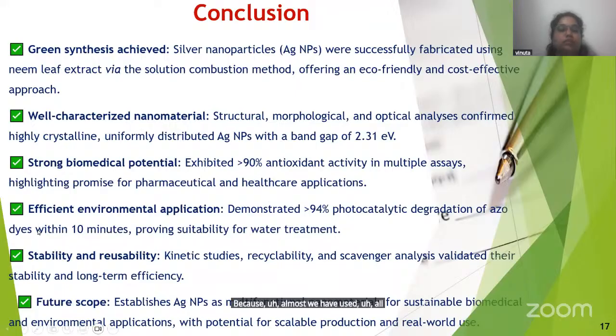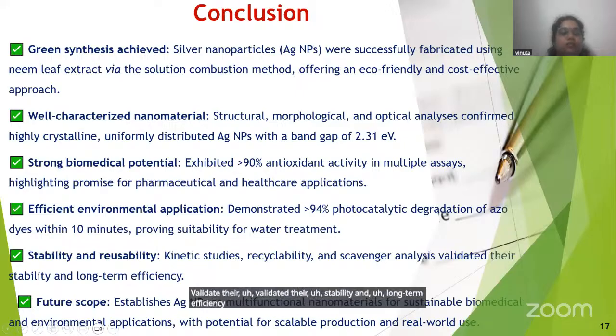So these showed 94% photocatalytic degradation of azo dyes, because we have used almost all the azo dyes, within 10 minutes, providing suitability for water treatment, mainly acidic water. So with the help of kinetic studies, recyclability, and scavenger analysis, their stability, long-term efficiency, and reusability were validated. So these silver nanoparticles show multifunctional nanomaterials for sustainable biomedical and environmental applications, with potential for scalable production and real world use.